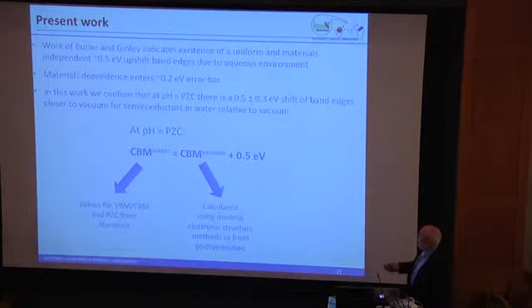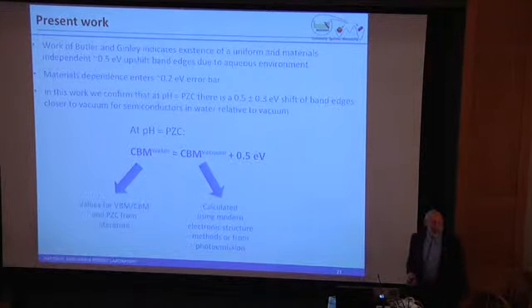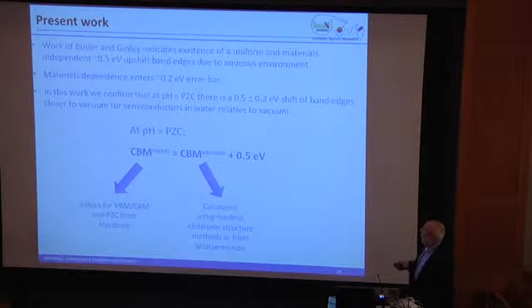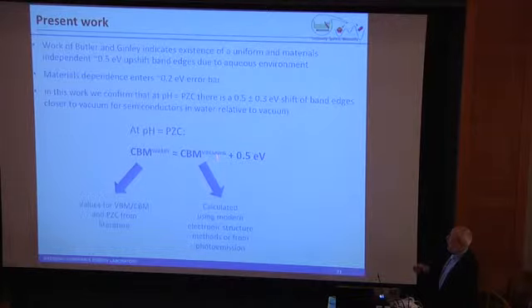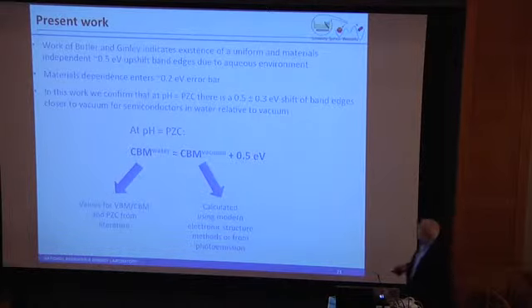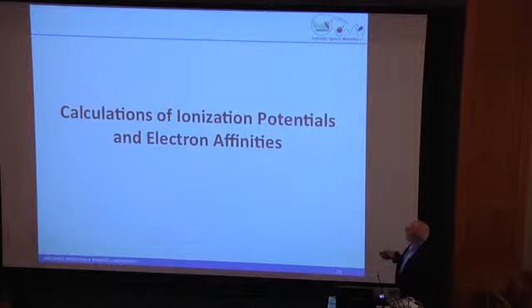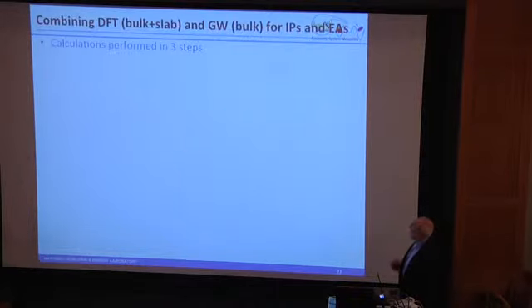So then, if we can calculate the values for the CBM in water, which we can equate from a CBM value in vacuum, plus this 0.5, then we have the CBM value in water, at least conceptually. So all we have to do is calculate this. Well, you have to figure out how to do that, because our standard methodology doesn't give you a calculated band position versus anything. It does it in absence of everything. So what we're going to talk about is how we calculate the ionization potentials and the electron affinities.